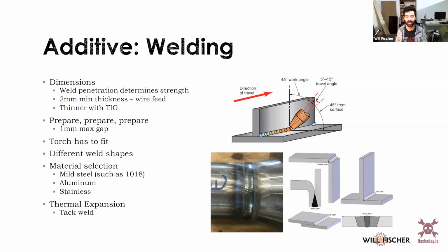So if you were going to do a long weld like this lap joint, you would tack it in multiple locations, so that before you started welding, while the material is all still cold, you tack, which I usually say is about a 3-second weld in that location, to make sure you bond those pieces together. And then you do your whole weld. And what happens then is, as the material heats up, your tacks prevent things from shifting around. And when everything contracts back, it goes back to the shape that you were in.